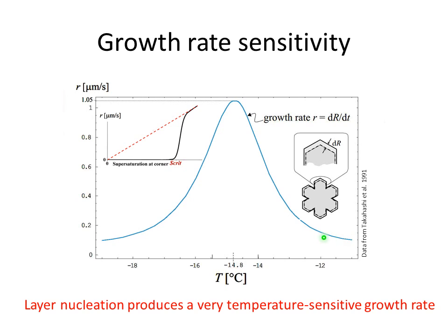But as we decrease the temperature just 5 degrees, this growth rate increases by a factor of 10, reaching a peak near -15. Further cooling by 5 degrees brings it back down by the same factor of 10. Why? Well, as we cool down to -15, the supersaturation over ice, at liquid water saturation, increases.